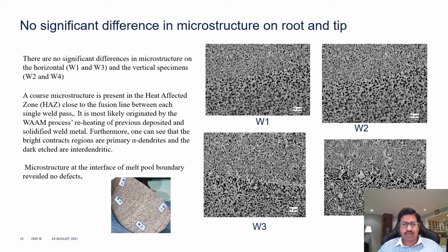And we took 4 samples at the critical part, in horizontal and vertical directions, and sent them for testing. We were interested in seeing the metallographic microstructure at the root, which is at the base, and at the top, since it goes through more thermal cycles. We wanted to check the effect of the heat affected zone between the two layers. But when we looked at the macro, we found there is not much significant difference from the base to the top. That means it has gone through the same heat cycle, and also there are no defects in the inter melt pool boundary area.